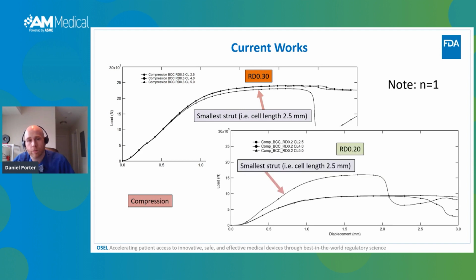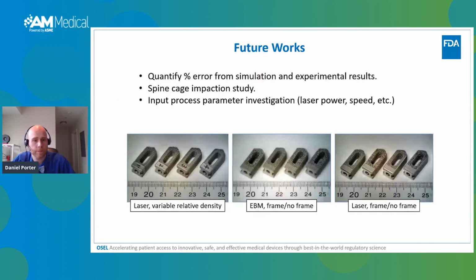Now, when we actually reduce the relative density, so we're using the smallest strut diameters now compared to the top left graph, it is actually the smallest strut diameters that were way stiffer than the two larger strut diameters, which is very interesting for us. And so we're going to look into this and see why that may be, because these are some considerations we might have to take into account when creating standards.